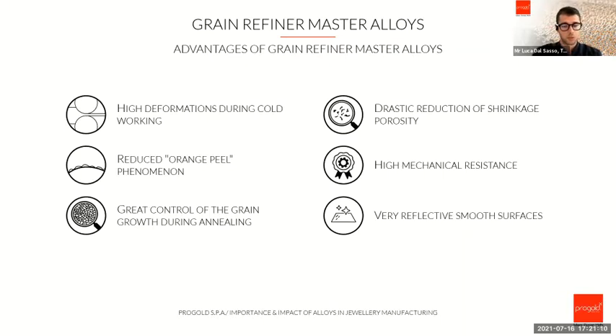A visible advantage of these master alloys that we will see also later is that the orange peel phenomenon is really reduced, because we will see later that a microstructure with a fine grain gives a smoother surface, as we were mentioning, and so the orange peel effect is really reduced. We don't have this big difference between the lowest part and the highest part of the surface. The grain growth control during the annealing is fundamental, just to reduce the orange peel phenomenon. And as we were mentioning before, you can see it also from the side of the sheet. It's visible even with the eyes, but also with a metallographic attack you can easily find out the difference between a fine grain alloy and a standard alloy.